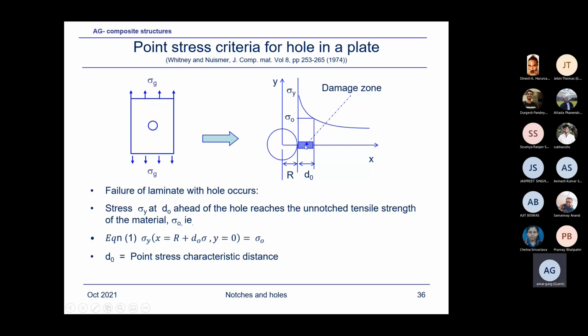And this damage is relieving the stress because the stress concentration factor is reducing. So this is behaving like plasticity, and that means this peak will drop. The effect of this is the development of the point stress criteria by Whitney and Nuismer, which is